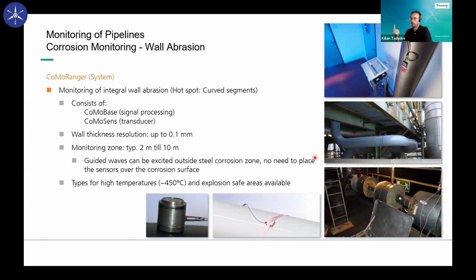You can fix the distance between your sensors. And then if you just measure the time of flight between 2 sensors, you can measure the velocity of the wave between these 2 sensors. And by using the relationship between velocity, frequency, and wall thickness, you can recalculate the wall thickness of your pipe in the section between your sensors. So this is the easiest case of a sensor system. Different sensors, a measurement hardware, and then a monitoring zone, a zone that is monitored for corrosion.